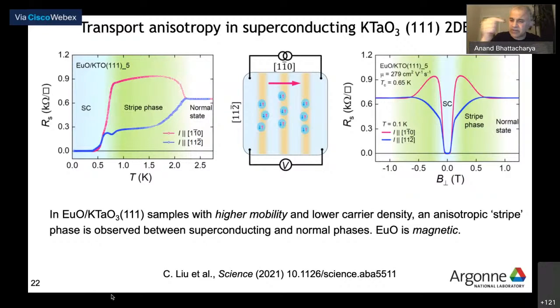going along one particular direction on the edge of the sample, this is current along 1-1-bar-0, which I'm going to call the hard direction sometimes, the resistance actually rises, then it settles down, and then at some lower temperature, it crashes down to zero. In the other direction, the easy direction, the resistance comes down, then again, it flattens out a little bit and then crashes.